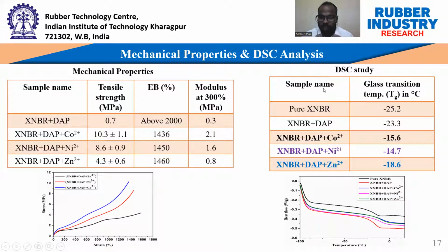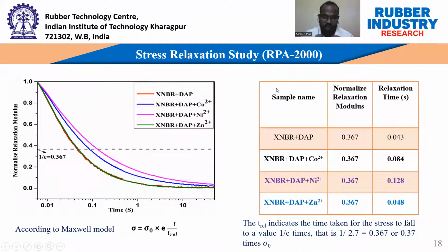After that, we performed the DSC analysis to understand the thermal behavior. In the case of the epoxidized natural rubber, the glass transition temperature is minus 25.2, and after modification with the DAP ligand, the glass transition temperature increases to minus 23. After addition of various metal ions, the metal ligand coordination bond was formed, and that's why the glass transition temperature also increases. For cobalt, the glass transition temperature is minus 15.6, for nickel it is minus 14.7, and for zinc it is minus 18.6.